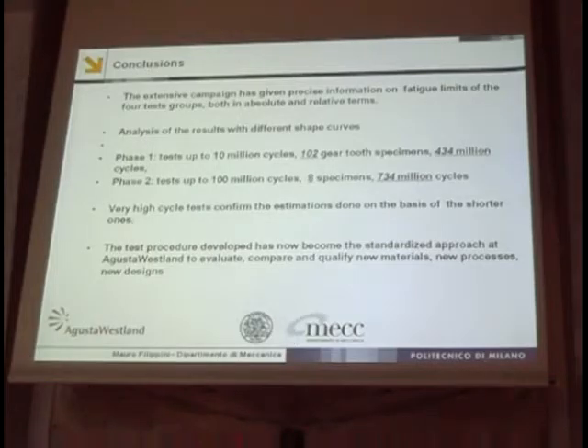So I come to the conclusion. This activity is going on. We still need to analyze the data in more detail, but we can say that we have precise information on the fatigue endurance of the four test groups, both in absolute and relative terms. We have analyzed the results with different models of the fatigue life. Of course, this activity must be refined, because at the moment we are analyzing the data with the common practice of the industry.